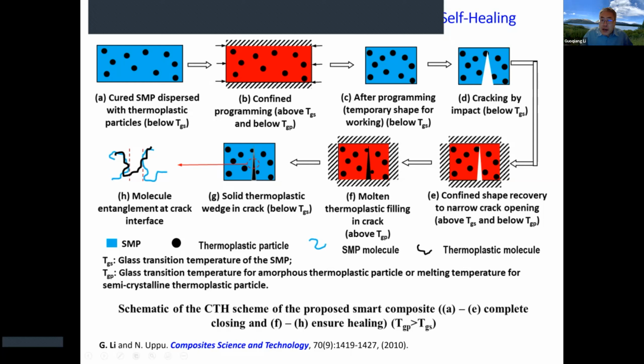Okay, what you do is heat up locally surrounding the crack. Once you reach a certain temperature, this shape memory polymer matrix will remember the original shape. That means it's here. So it is trying to expand in volume. However, surrounding this hot zone is cold material, so the free volume expansion is not allowed. Instead, it must be pushed inside the open space. In such a way, you see the crack can be narrowed or even closed.